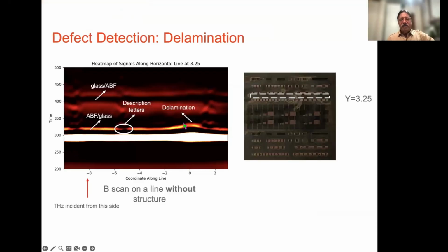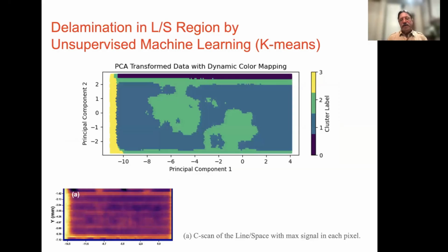We can also see delamination. We'll see this also in the subsequent slide. These are areas where there are bubbles, or regions where the layers did not fuse or incorporated air bubbles inside. We can also see that from the top using clustering methods. Here's an example of unsupervised machine learning, seeing some incorporated air in rather large regions. We see inhomogeneities in a plain C-scan based upon the maximum signal, but this cloudiness is not necessarily connected to delamination. We see this kind of cloudiness where there is no delamination as well. So we really need this sort of analysis to extract these regions where there may be delamination.